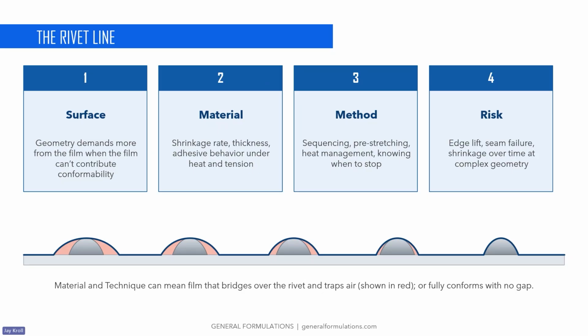So calendared film with a less robust adhesive has memory pulling it back towards flat over time. And that shows up like we see on the left there with that tinted film over the rivet, versus something that maybe is a thinner film, a more conformable film, a more aggressive adhesive that will tip the scales towards the right-hand side where we've got a successful install. But again, even cast vinyl can fail here if it's not installed with the right balance of heat, pressure, technique, all of that.